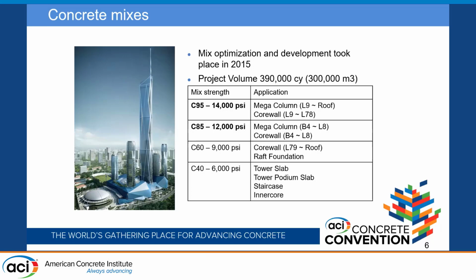It was determined for the very high strength requirements that 56 days was the minimum PSI requirement, and 90 days was best, especially for the modulus of elasticity. The later age acceptance requirements became key to optimizing cost, energy, and materials. And I can't stress that enough. As I spoke to the folks involved with this project, it wouldn't have been possible to optimize the mixes and achieve what they achieved on this project without pushing out the acceptance age to 90 days in some cases.